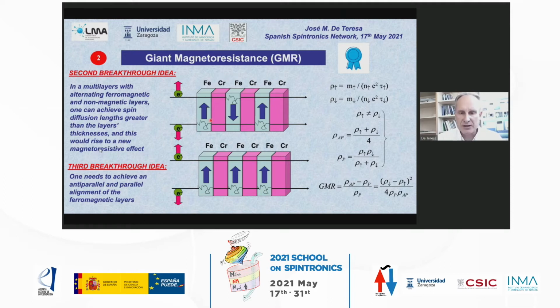This is the giant magnetoresistance. So for that, what one needs to compare is the resistance when we have an antiparallel magnetic configuration of the ferromagnetic layers with the resistance in the case of parallel alignment of the magnetization of the ferromagnetic layers. So in a simple way, you can calculate the resistivity in this antiparallel configuration by taking into account the resistivity of the spin-up channel.